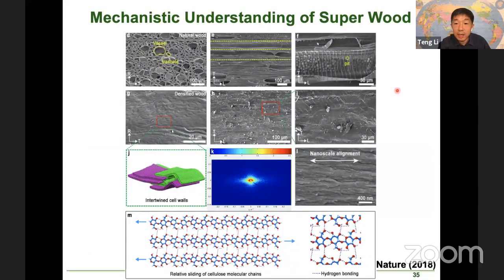So here, I think it's a better image. As you can see, these are the four images I showed on the previous page. If you look at F, you see these tiny pits on the surface of the cell wall. You know, for mechanics people, anytime you see defects, you know something is troublesome. Now, after the densification, you see that even those tiny pits disappear. So we can almost always manage a full densification of natural wood to remove most of the defects over there. And this is the alignment of the cellulose nanofibers.